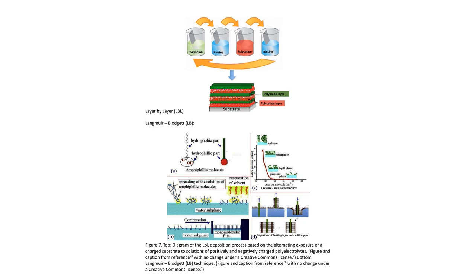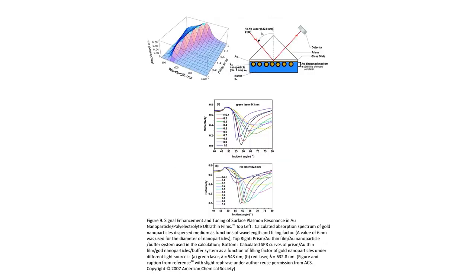Their work has shown how EC-SPR can reveal changes in nanostructure and dielectric properties in these highly ordered films, which is critical for applications in solid-state devices. A particularly interesting application they explored was using gold nanoparticles to enhance and tune the SPR signal. They investigated a system with an Au nanoparticle and polyelectrolyte layer-by-layer film.